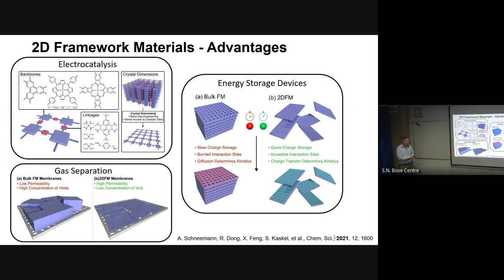For gas separation, you imagine a membrane. So this is an example of an aluminum oxide membrane that has pores, and you cover it with a bulk framework material with bulk crystals. The diffusion will be much slower. The permeability will be much lower, in contrast to having just a very thin layered structure. And you also can imagine that these crystals will arrange not in such an ordered fashion in comparison to the sheet materials, and you will much more easily form voids and cracks in the structure covering your support than if you have these kind of sheets that you just lay on top and then glue to it with some things.